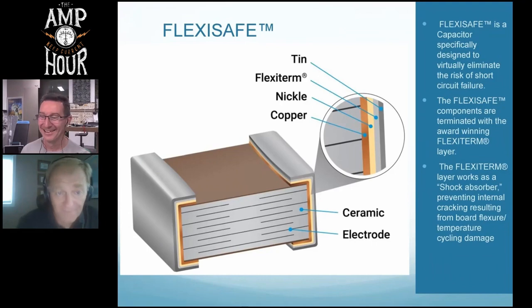Very cautious. And I'll have to say that the flexible terminations have gotten very good, because there is a military spec, 32535, and they actually call out the use of flexible termination material sets. Got it. And there's multiple suppliers to that. But truly, as end users, they should be careful to make sure that termination is stable with ESR and under environmental conditions.